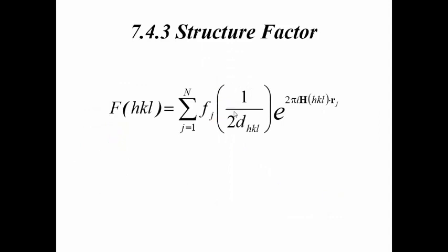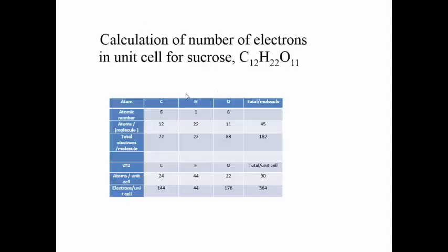Okay, in this final situation, we're going to put the whole story together. This is the formula for the structure factor. This is the part contributed by the atoms. This is the Cromer-Mann curves that you have done for each of the individual atoms. The j is over the atoms. And the position of the atoms, of course, contributes to the structure factor, and that is given by the phase angle. And finally, we have to sum it over all of the atoms in the unit cell. But we're going to be doing that and looking at those equations for your crystal.